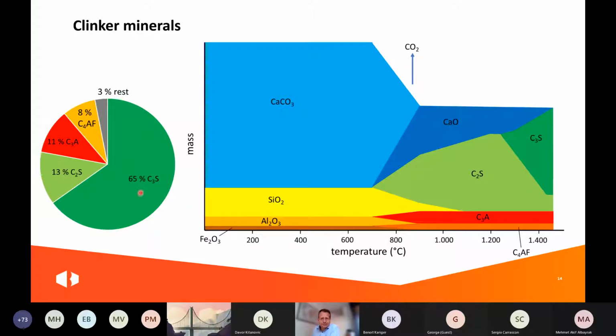So here you see a composition of modern Portland cement. We mainly have the C3S, a little bit of the C2S, the belite, and those components with aluminium and iron we actually don't need, but they help to keep the burning temperature a bit low, and those are coming from the clay.